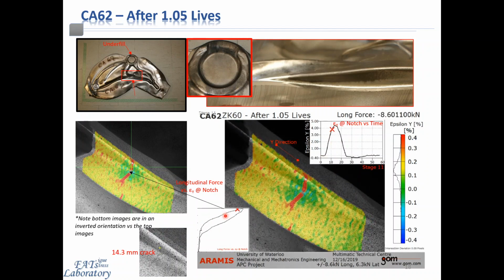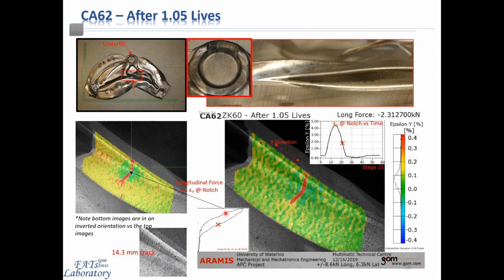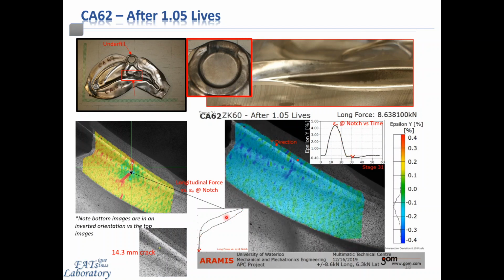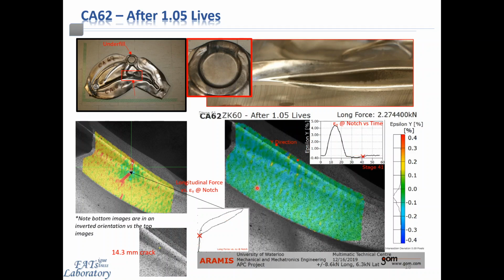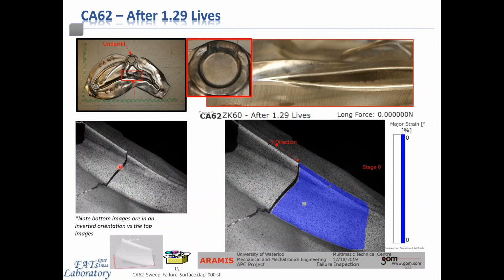Now increasing to 105% of the fatigue block cycle, the crack has now grown exponentially to 14.3 millimeters in size, and we can see further localization of the strain field in the same region. Finally, the component failed at 129% of the target fatigue life, and this slide summarizes the crack plane, which initiated at the location right here at the edge of the forging radius of the particular component indicated here. We don't know yet if it was a forging defect that was the cause of the crack initiation at that particular location, but I'll discuss that in a little bit more detail shortly.